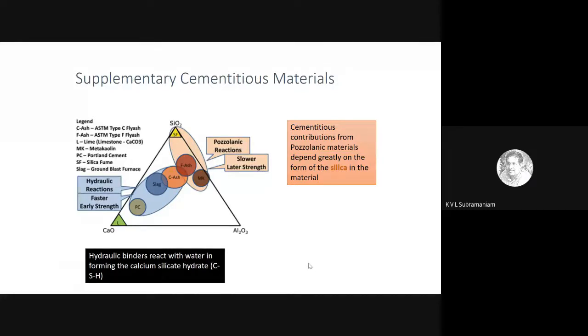Slag is quite close to PC, which means basically slag would be mimicking cement, and therefore I can look at a higher level of replacement of cement with slag, and that's the reason why when we are replacing cement with slag, we are able to go up to 70% replacement without sacrificing strength. Similarly, we can work out for all the other materials, and remember, most of these are post-industrial waste materials, except metakaolin, which is basically a manufactured material, but most of the other materials are post-industrial waste. They're waste materials derived from other industry.